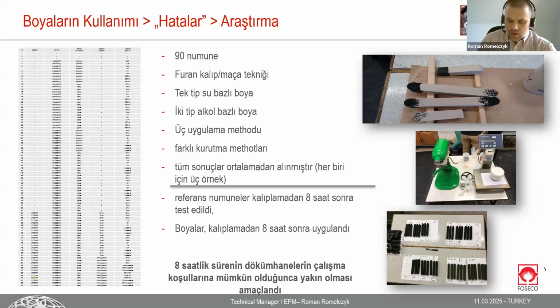So each bar which was checked in the transverse machine was exactly in the same curing stage of the process, to be super precise with the readings. These samples were covered with different coatings. One was ZKX. ZKX is nothing more than a zircon-based coating. It's an impregnation coating, which impregnates only the core or mold, to improve the refractory behavior of the core or mold.